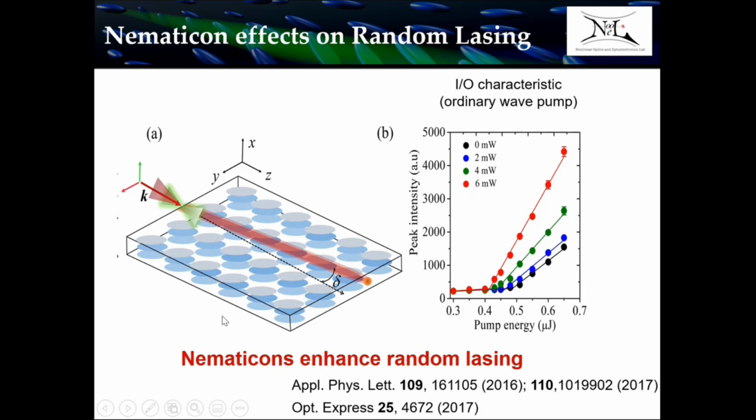And so we launched both beams in the cell, moving the molecules in the plane by means of the near-infrared beam to make a soliton. And then for various continuous powers of the soliton beam, at milliwatt power levels, we could study the pumping threshold of the green in order to induce random lasing.